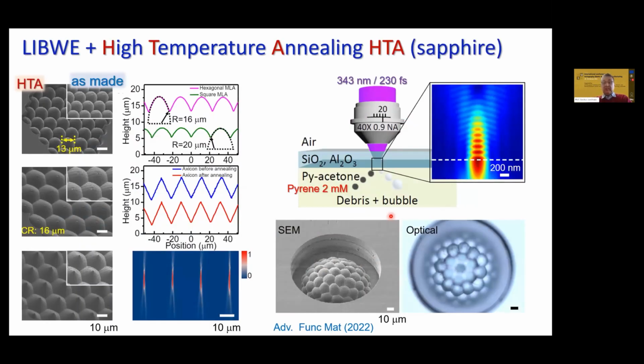Okay, so now let's go to more recent things where we are using fabrication of micro-optical elements, in this case in sapphire. One thing which is added here is high temperature annealing after you ablate your 3D surfaces. And ablation also here is done in a slightly different way. You are focusing the femtosecond pulse on the backside of the transparent material, and this way allows you to avoid any debris formation and flying into your incoming laser pulses. So it's removed from the interface by cavitation.